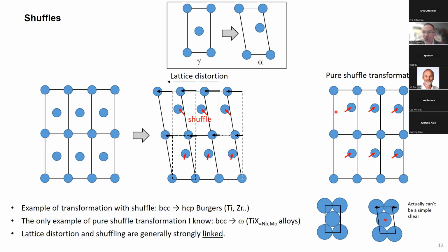We can even imagine a transformation with pure shuffle. It means that we do not change the lattice. The lattice is exactly the same, and it's just the position of the atoms in the center that move. Well, it's very, very rare. The only case I know of a pure shuffle transformation is the formation of omega phase in titanium niobium alloys, for example.